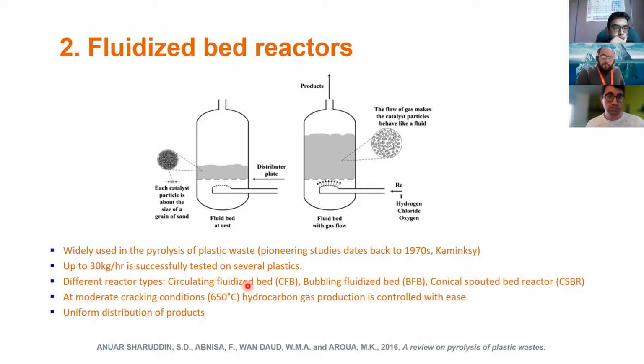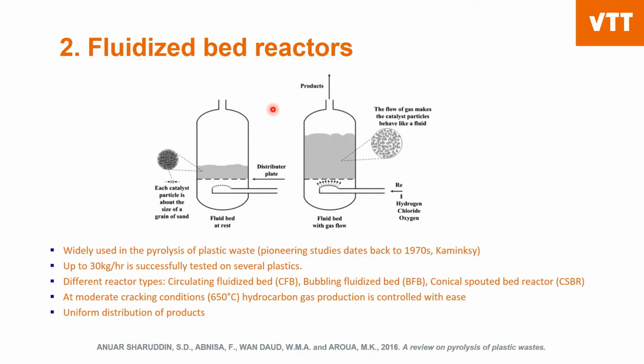Circulating fluidized bed means that the bed basically is entrained into a vessel, is regenerated, and then transported back into the reactor. So the bed is moving out of the reactor, goes into the vessel, and then comes back, and it's circulating. This is called circulating fluidized bed. This is very advantageous when you have some sort of a catalyst as a bed material, because in the second step you can regenerate the catalyst and bring it back, so burn away the impurities or the coke from the surface.